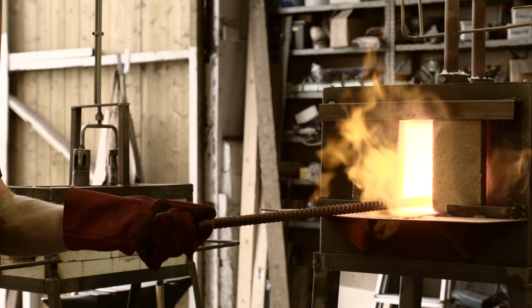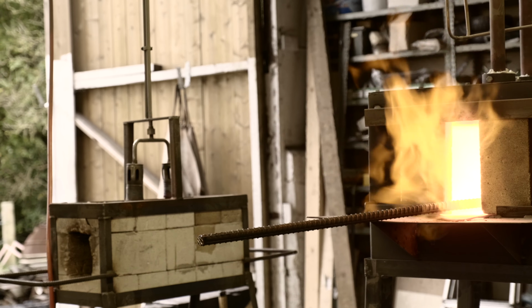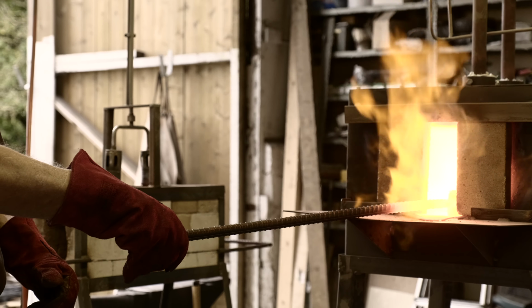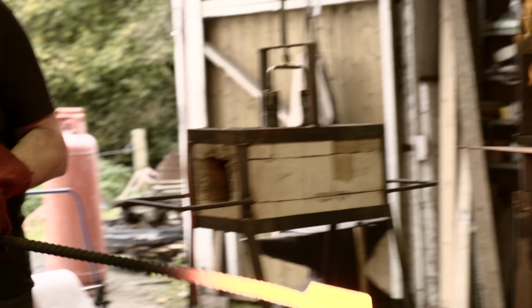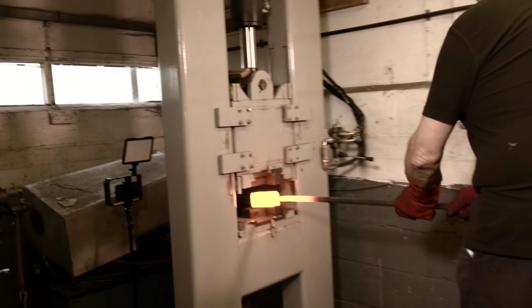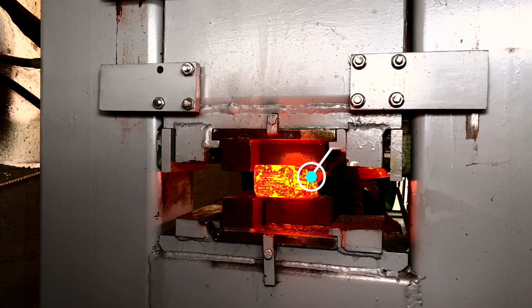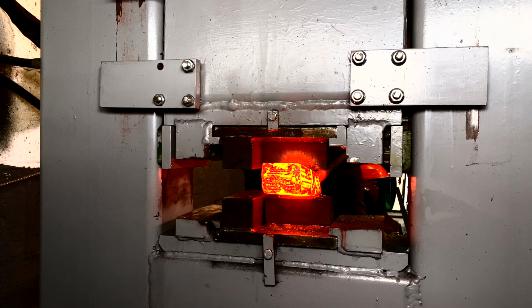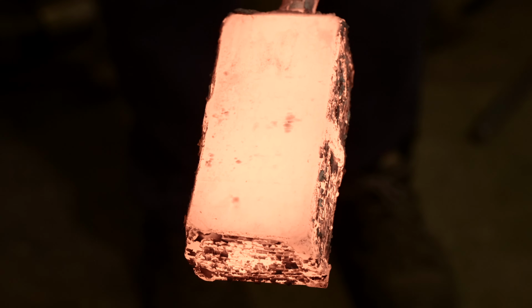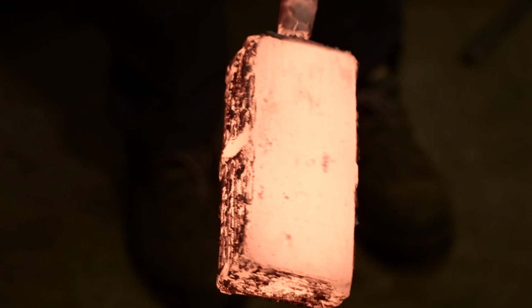Right, so it's coming nice and hot again now. So now I'm going to start forging down, pulling those layers out to make them much thinner and longer, ready for restacking. It goes into the forge a little bit at a time. That's it. There we go. You can see all the layers on the side. They're getting thinner as the billet gets bigger. I'm going to start making that from a rectangle now more into a square billet.